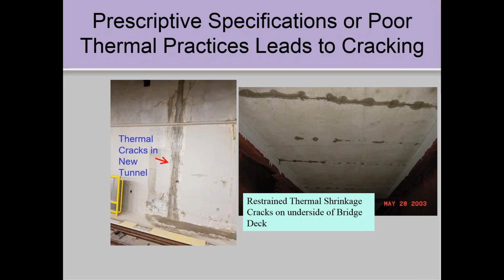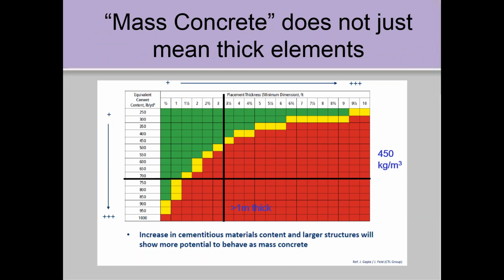On the left, you've got a brand new subway station tunnel. The station hasn't even opened yet, and they're repairing cracks that are leaking because of thermal. There were thick walls, and they were restricted in their mix designs, and they couldn't avoid it with the mix designs they used. But hopefully, if they use this thermal control plan, they could avoid that. And the one on the right is a picture of an underside of an MTO bridge deck that was cracked right through the deck, right at the get-go before they waterproofed it, and the water's leaking through. And those are thermal cracks, transverse cracks in the deck.